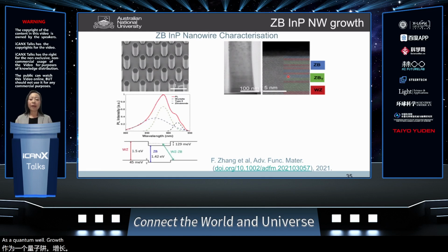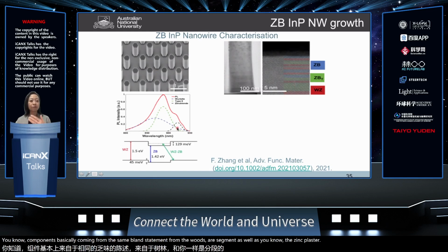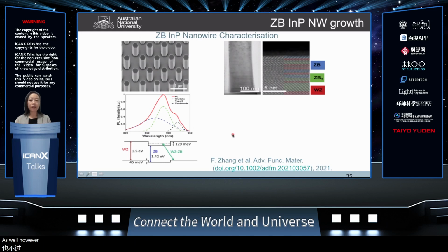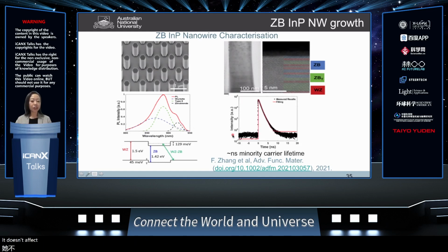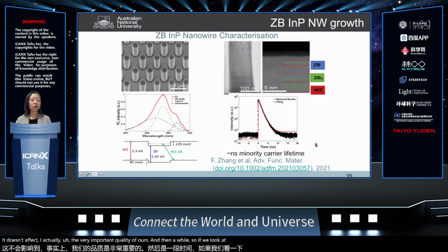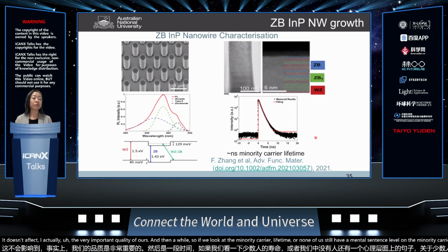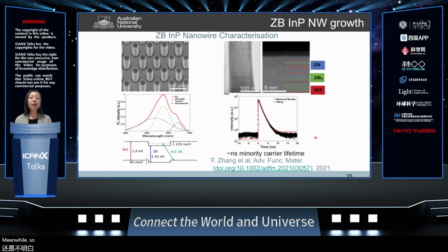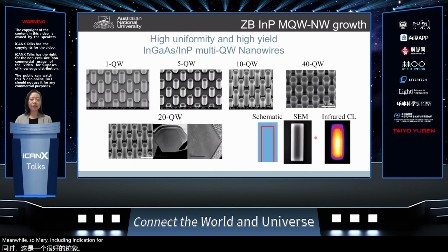And of course, if you look at the PL, it shows it's not only a broad peak, rather it has quite a few different components, basically coming from the zinc blende segment, from the wurtzite segment, as well as the zinc blende-wurtzite transition as well. However, it doesn't actually affect the very important quality of our nanowire. If we look at the minority carrier lifetime, our nanowire still has a nanosecond level minority carrier lifetime, which is very similar to our wurtzite-based stacking fault-free nanowire. So very good indication for device.